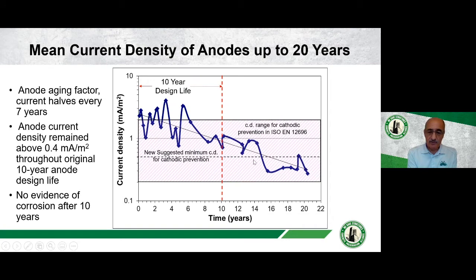Another thing that we noticed is that beyond the 14 years, which was the time when the patch repair was working well and then we had the initiation of cracking, the current had dropped significantly to a value lower than 0.4 milliamps per meter squared. Now the standards still say that your current density can be between 0.2 and 2 milliamps per meter squared, and although we're within that range, obviously we weren't protecting the steel reinforcement adequately in that situation.